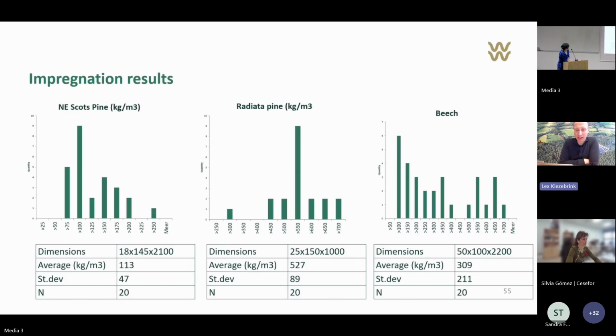Yeah, so the impregnation results are shown here. The different wood species have different characteristics and also different uptakes. You see that the average uptake of radiata pine is the highest, which is also according to expectation, and also at a level that's good enough for decent performance. The beech shows really high variability, which was also more or less expected. But what we didn't expect is that we had less variability in the Scots pine, and also we saw that the penetration of the sapwood was not fully penetrated with the impregnation solutions.